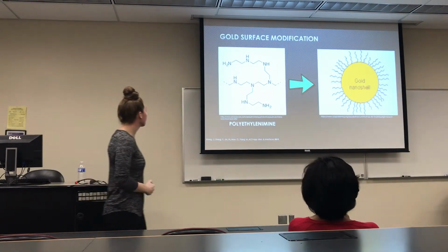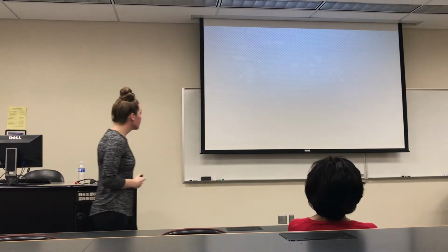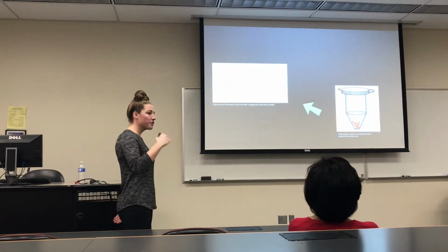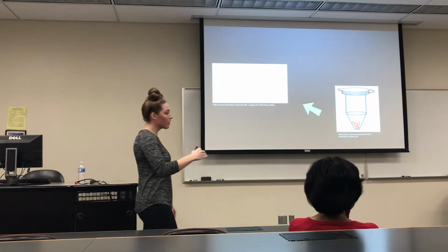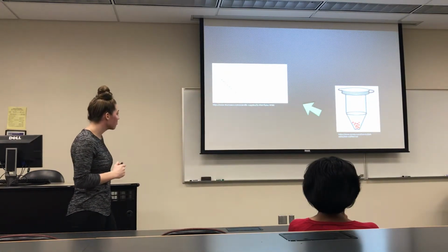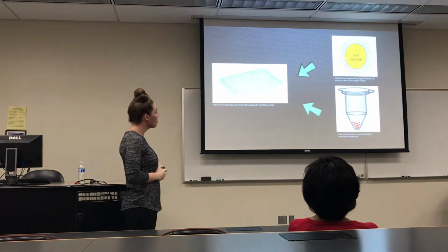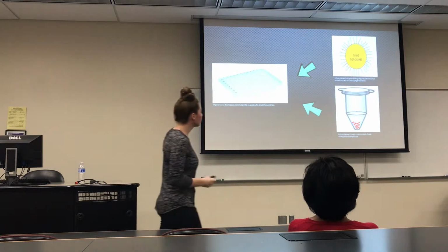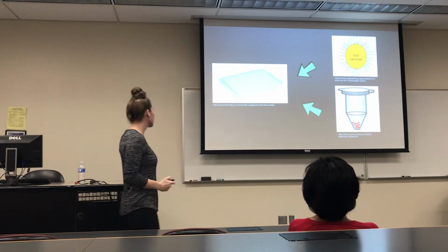So in order to facilitate this, hopefully with our aggregation template, I went ahead and used a 96 well plate, and I introduced different concentrations of DNA. So I started out with a non-dilute concentration and then did a subsequent 100-fold, and from there did serial dilutions of 10-fold. So I ended up with about 5 samples. And to that I added consistent volumes and concentrations of those gold nanoparticles with the PEI modification.